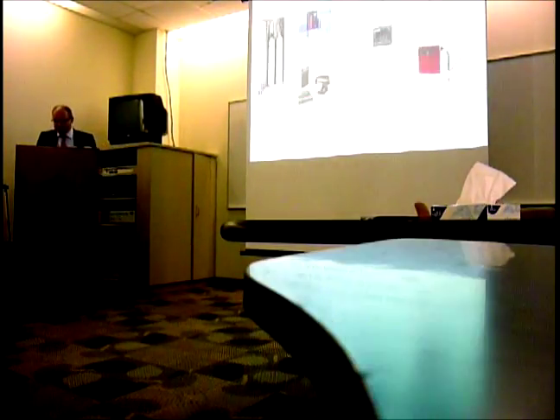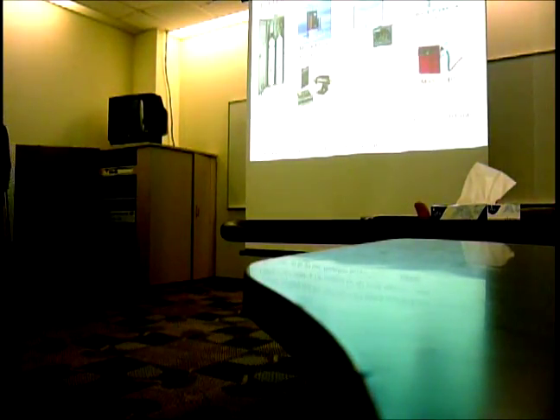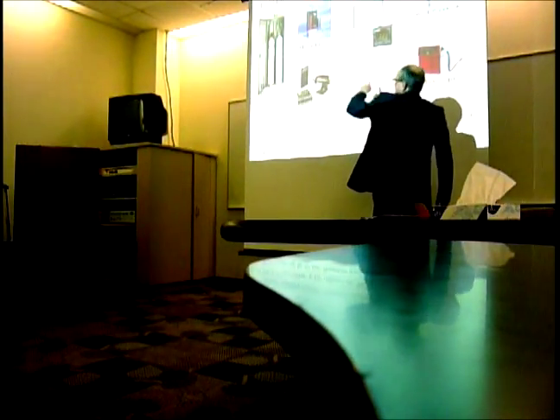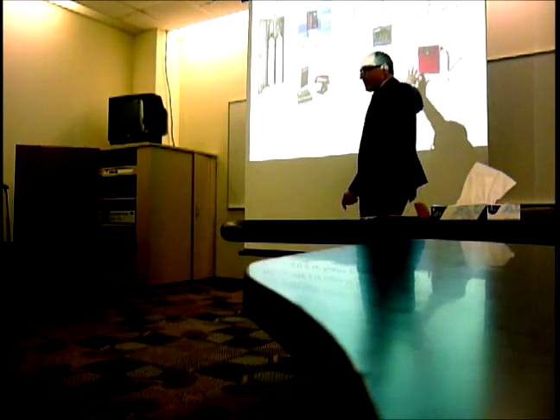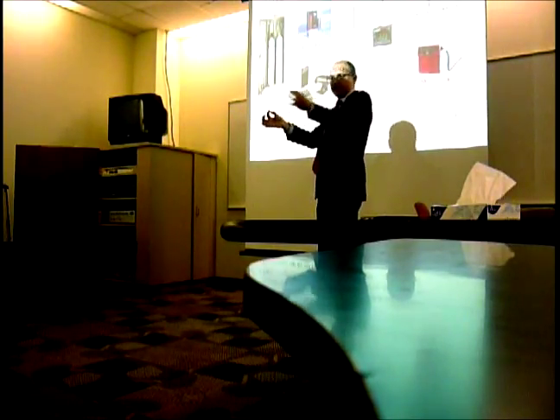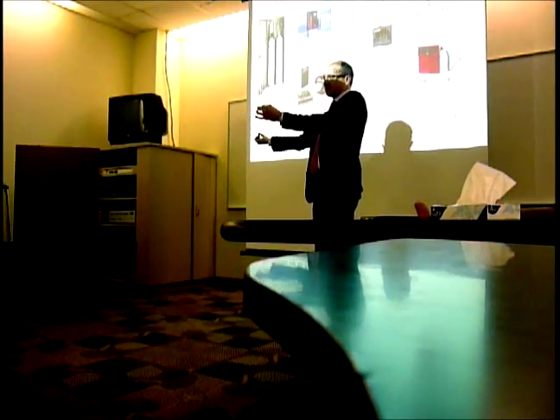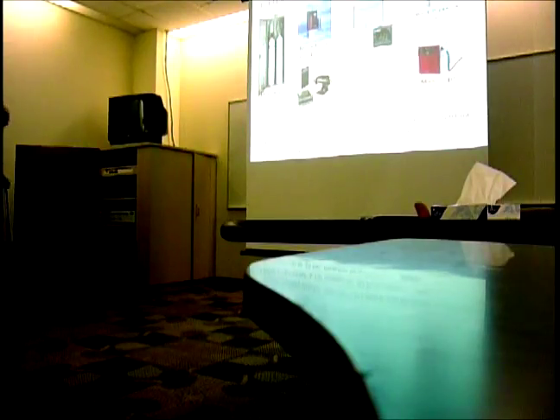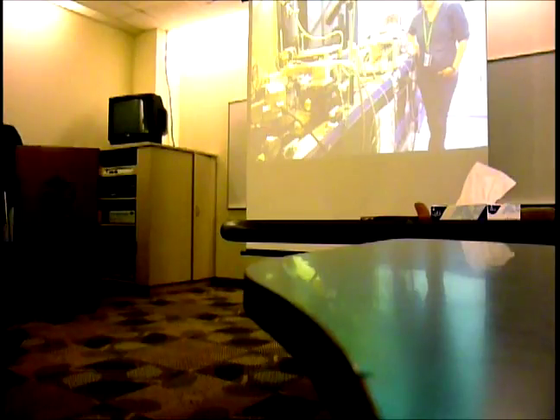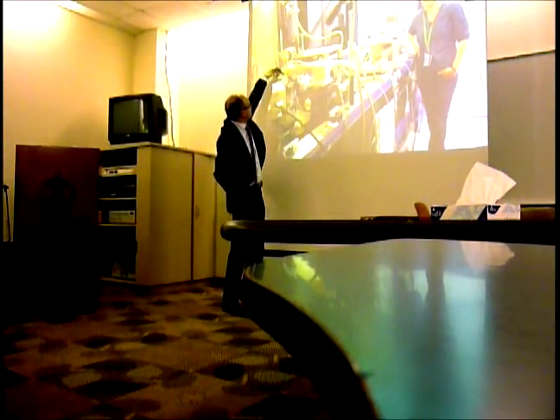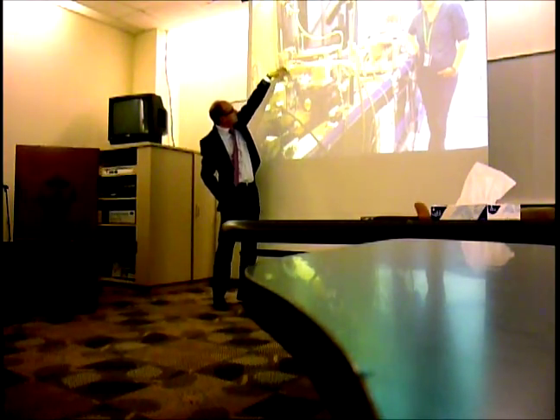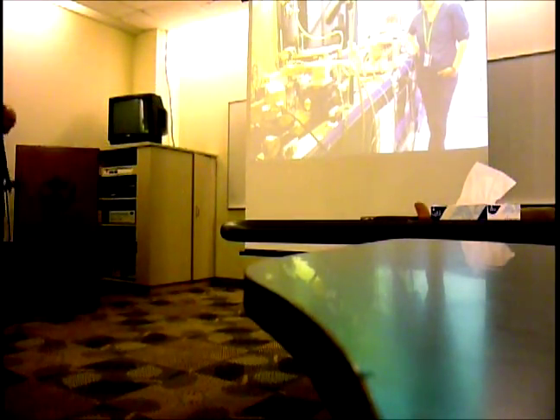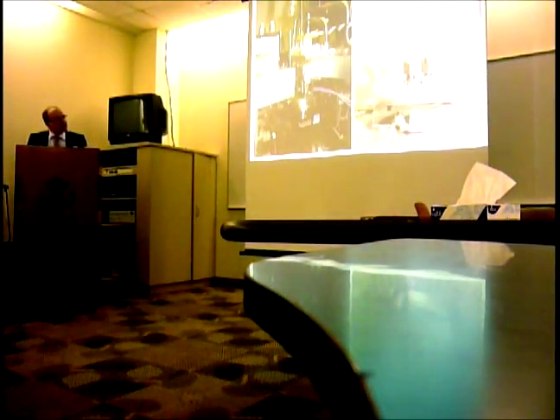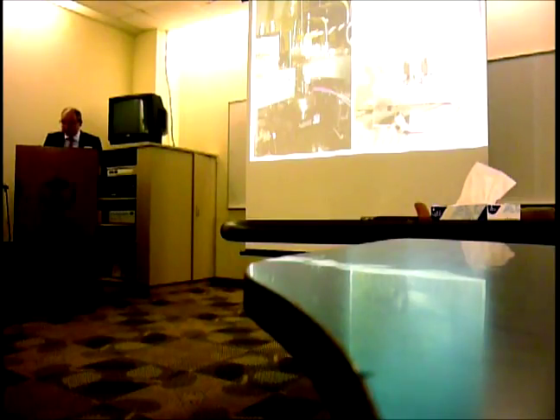Now this kind of setup we have been making ready for catalytic experiments. And so we have been building up an in situ cell, a device, together with gas delivery, a mass flow control system, and also a mass spec, which allows you to put a catalyst particle in this cell, bringing a gas through it, measuring conversion at the end, and at the same time measuring X-ray spectroscopy. And this is shown here in this setup, and the heart of the device is this. This is the heart of the device where you have the cell, X-rays going through, and here you can put on top of it a furnace, and then get in, get out, and you can measure. Just to zoom in, on the left is the heart of the device, and on the right you see a capillary which is positioned in between the holders where you can bring in gas. I can tell you it is far from trivial to make and make it work, so it often fails.